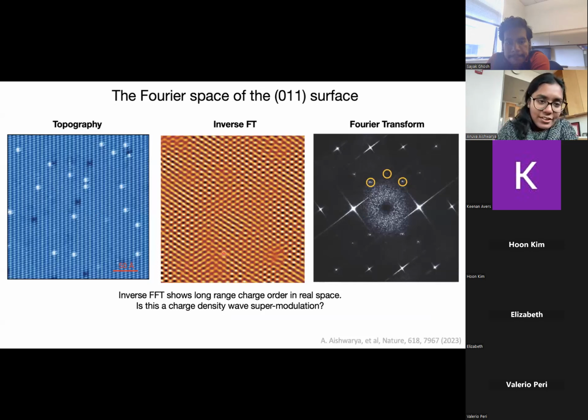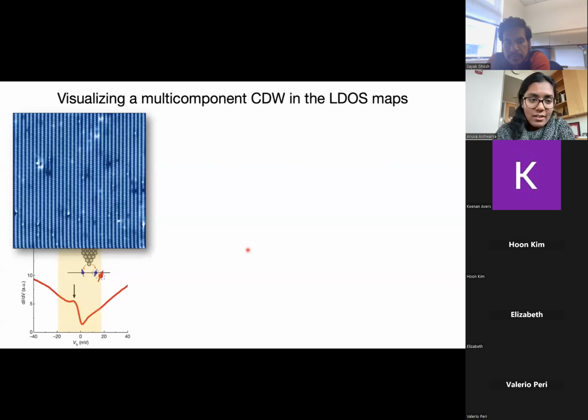We can see it in the inverse FFT. Now the question is: is this a charge density wave supermodulation? We can actually look at the density of states maps, as I said before, and see what the charges are doing. So this is what we did in the next part.